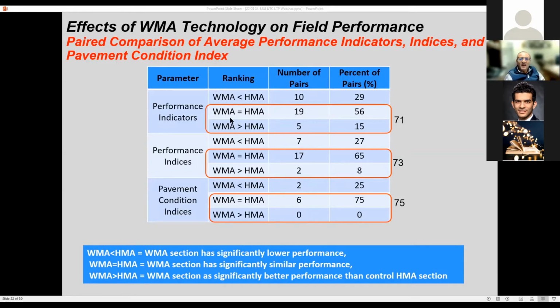And what you see here is that in those mixtures where WMA was at least equal in performance or better than hot mix asphalt, we had 71% of those pairs of those 34 systems that we compared. In terms of performance indices, the similar statement increased to 73%. And in the PCI world, it increased to 75%. So that kind of gives you an indication of how WMA technology did in the field in terms of measurement. So that's kind of the first objective we looked at.